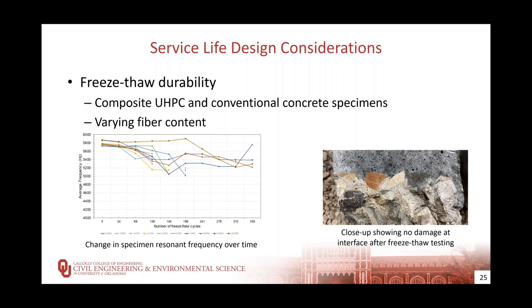The graph shown here presents the specimen resonant frequencies over time. All specimens except the 4% and 6% fiber specimens eventually exhibited enough damage that it was no longer possible to obtain a frequency measurement. But again, the majority of the damage to these specimens was in the base concrete.